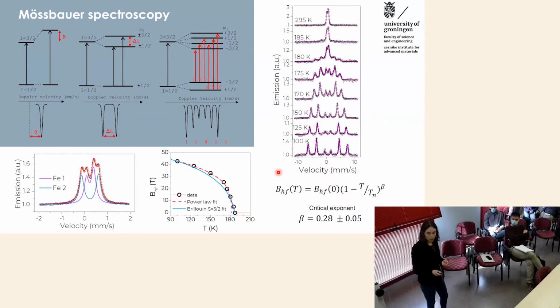This is called quadrupolar splitting, and it depends on the presence of some anisotropy in the bonding environment. And when the material orders magnetically, we can also have a splitting which indicates the presence of long-range magnetic ordering. We performed this experiment on our samples, and what we saw is that we have two iron environments, iron 1 and iron 2, which are the two irons in the crystal lattice of calcium ferrite. This was already telling us that there are no other iron-containing impurities in our films, and their shift corresponds to iron 3+.